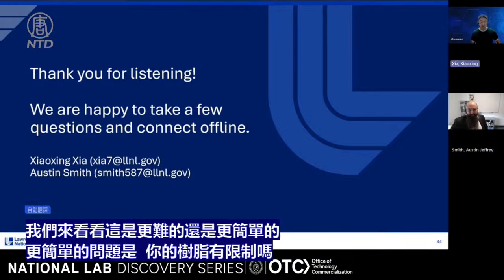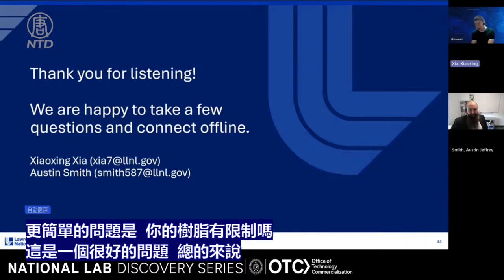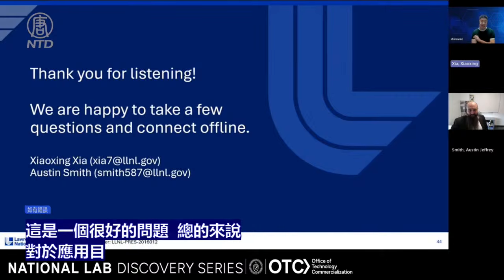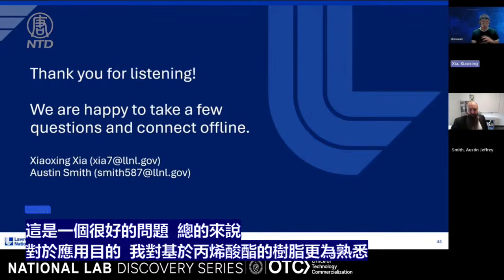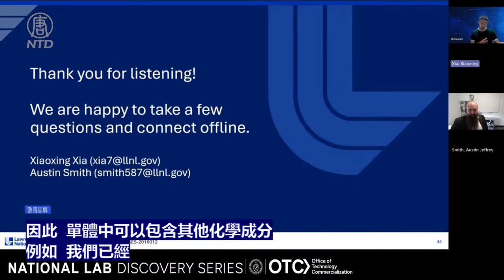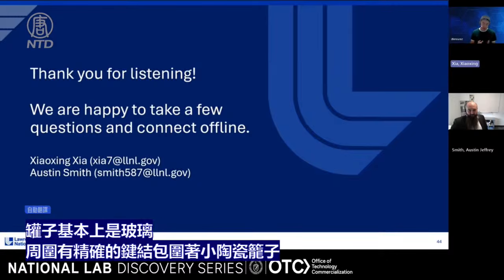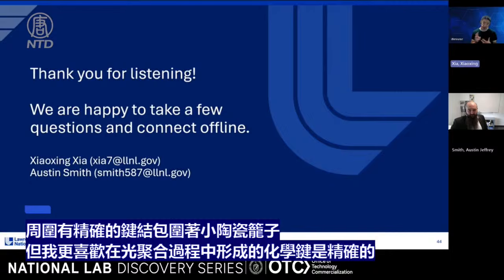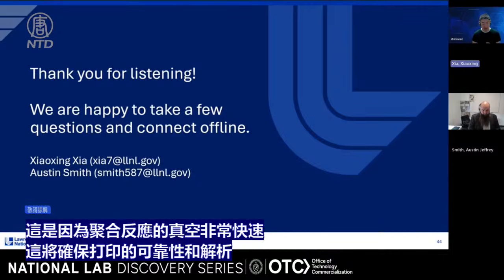It's a great question. For application purposes, I'm more comfortable with acrylate-based resin. The monomer can have any other chemical component in it. For example, we've done POSS, which is pretty much glass with acrylate bonds surrounding little ceramic cages. But I prefer the chemical bond formed during photopolymerization to be acrylate. This is because the polymerization reaction of acrylate is extremely fast, which gives really good reliability and resolution for printing.